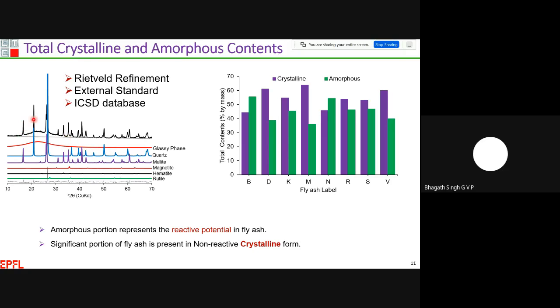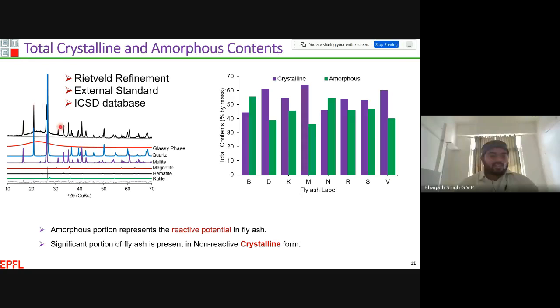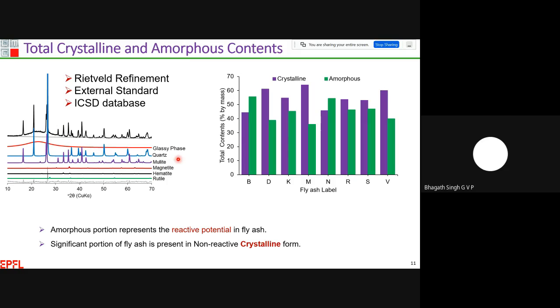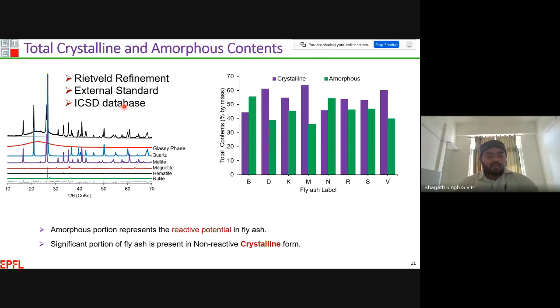And also we have different crystalline phases observed over the spectrum. And finally, I have identified what these crystalline phases are. I identified quartz and mullite as the predominant quantities, followed by magnetite, hematite, and rutile in minor quantities. Then I carried out the Rietveld refinement using the external standard approach, and determined the total crystalline and total amorphous content present in all these fly ashes.